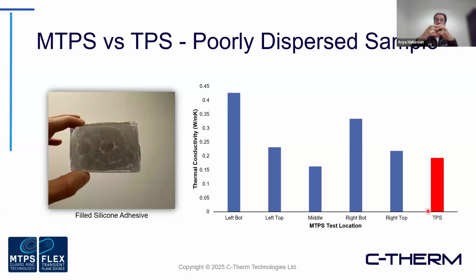So that heat pulse that's generated from the test is entering from the top and the bottom side. It's not directionally dependent. So it's this kind of average value spread out over the area of assessment versus the MTPS, which is the localized measurement at where it is placed on the sample. In terms of which value is right and wrong here, they're both providing you an output of thermal conductivity. TPS is simply averaging out that larger area, whereas the MTPS is more of that fine comb approach where we're picking up on some more localized differences.